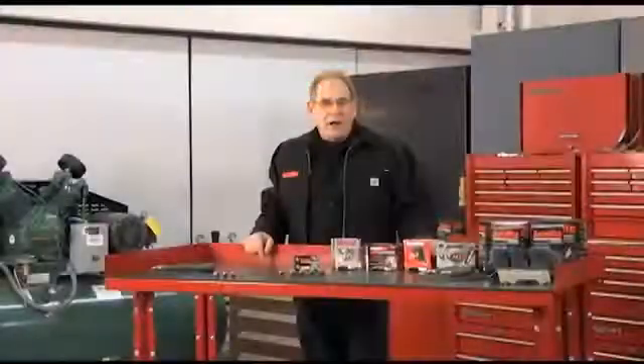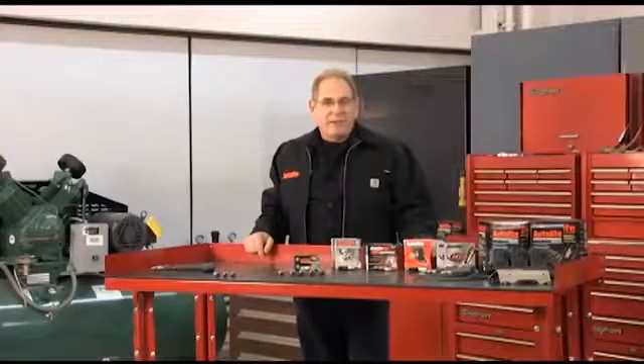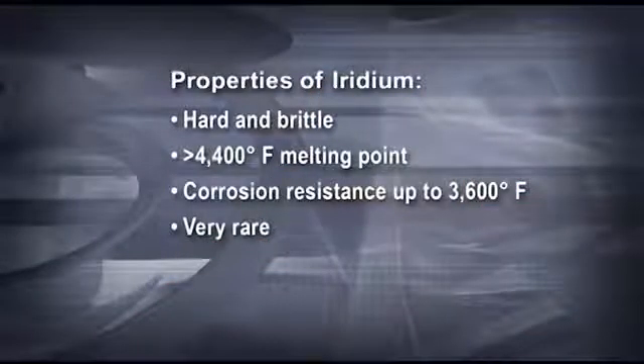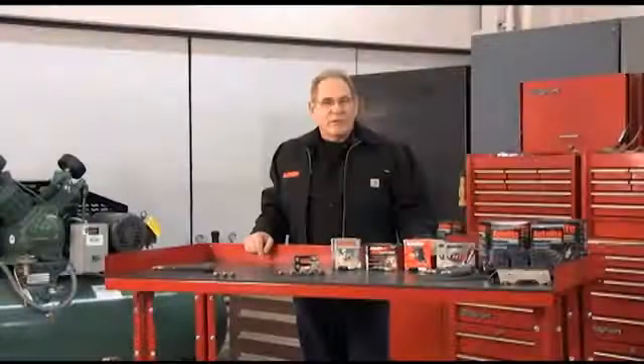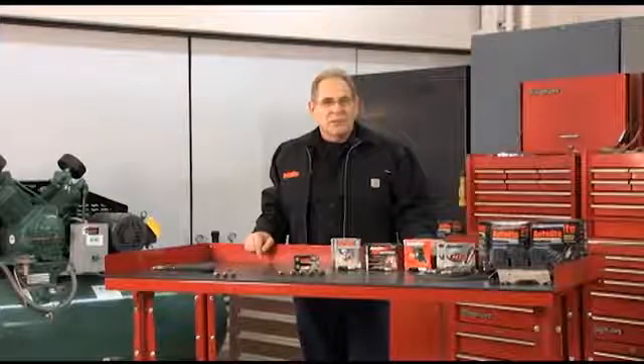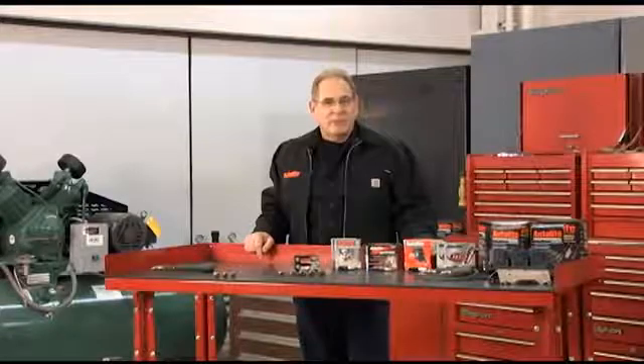Iridium is a very hard, brittle metal in the platinum family that has a melting point of over 4,400 degrees Fahrenheit. Iridium is the most corrosion-resistant metal known to man, even under temperatures as high as 3,600 degrees Fahrenheit. It's also a very rare element. By comparison, platinum is about 10 times more common in occurrence. As ignition systems further evolved into coil-over-plug systems and coil-near-plug systems, it was important to develop a more efficient spark plug that required less voltage to fire.